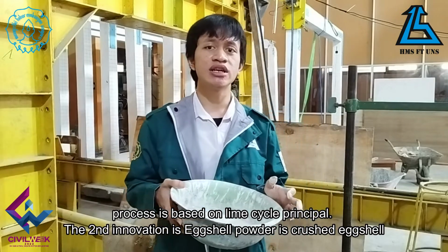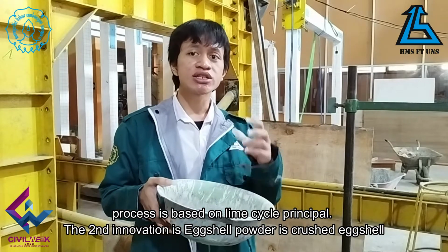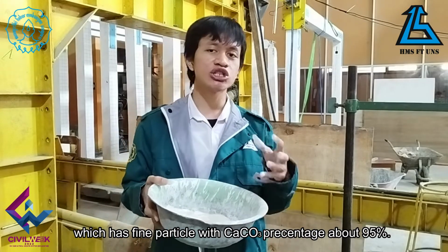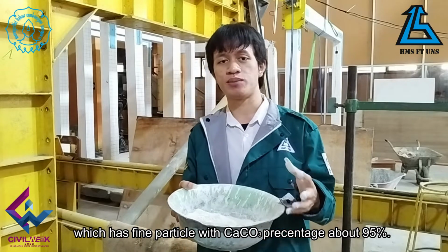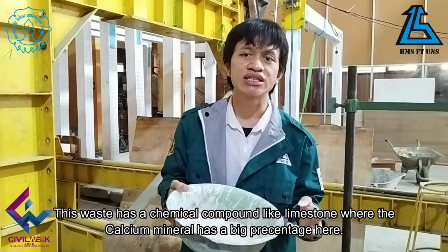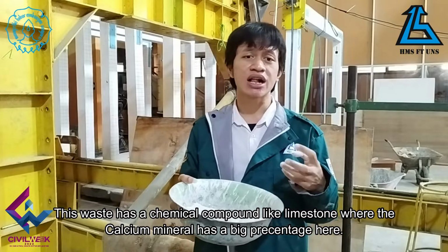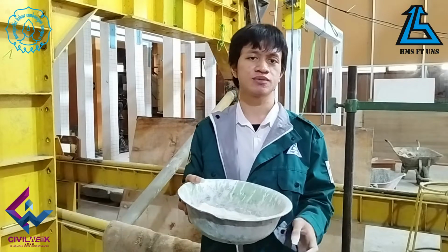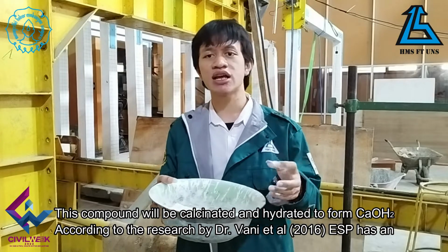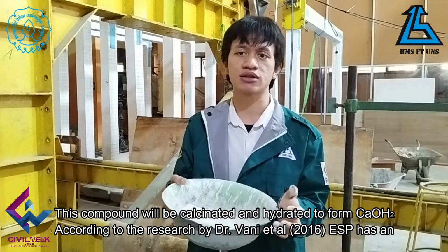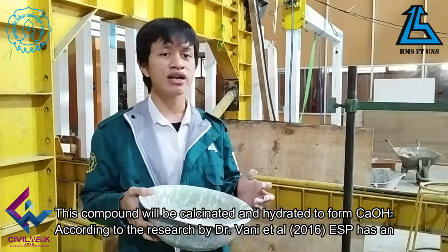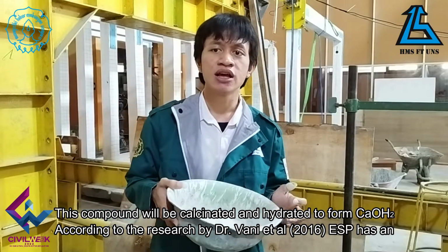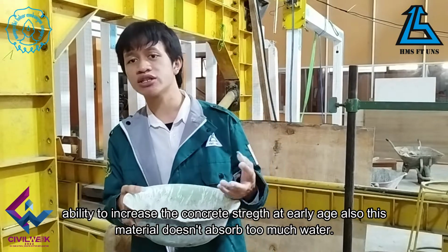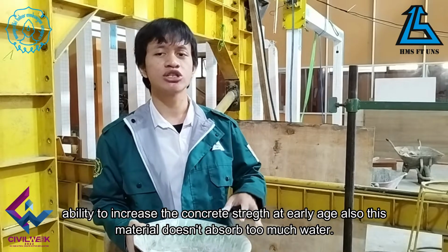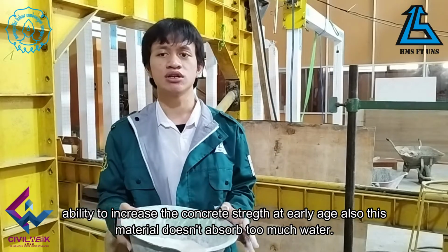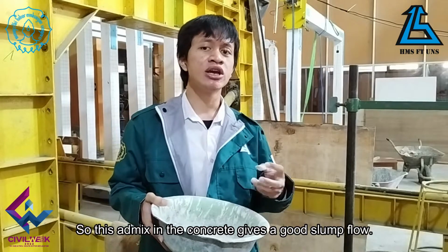The second innovation is eggshell powder. This is crushed eggshell which has fine particles with calcium carbonate percentage about 95%. This waste has a chemical compound like limestone, where the calcium mineral has a big percentage. This compound will be calcinated and hydrated to form calcium hydroxide. According to the research by Dr. Vani et al. in 2016, ESP has an ability to increase the concrete strength at early age. Also, this material doesn't absorb too much water, so this admixture in the concrete gives a good slump flow.